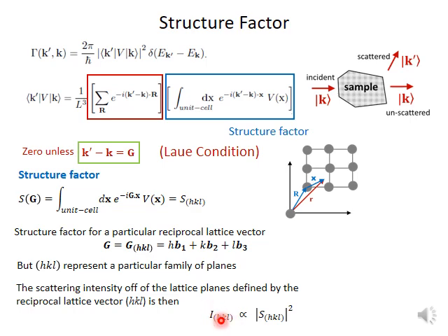But since this structure factor has a certain index, for a specific HKL value this intensity represents scattering from a specific family of lattice planes, and that's how you can interpret this whole mathematics. It is a very important statement, which we would use to identify the intensity of scattering.